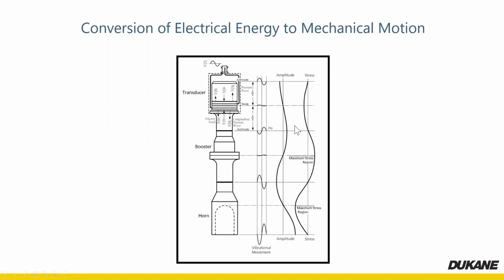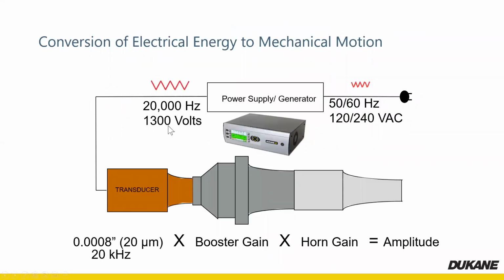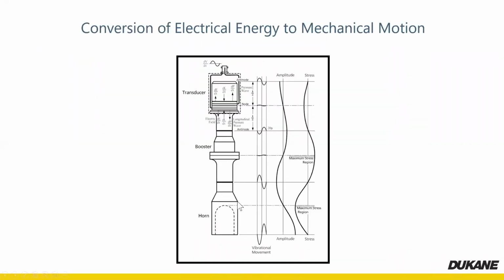So we're producing a decrease in power going into this transducer. If we go back to this slide, you can see we've got 1300 volts going in. That voltage actually has an impact on the amplitude. So if we reduce the voltage going in, we can adjust the amplitude coming off the face of this. In 1% increments, we can take that 20 microns and bring it down by 1% at a time. So 18 microns, 16 microns, 14 microns, et cetera. So you're reducing the input amplitude and therefore reducing the output amplitude. And generally we want to build and design a stack that's got slightly more amplitude than we need, and then fine tune it using that amplitude adjustment.